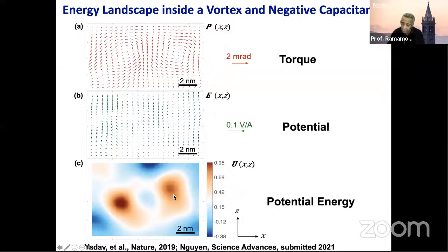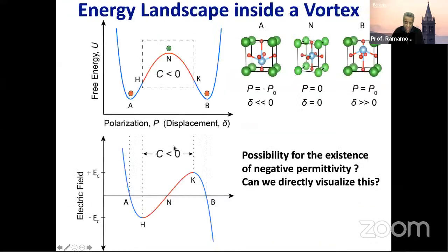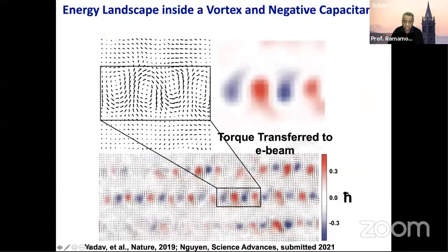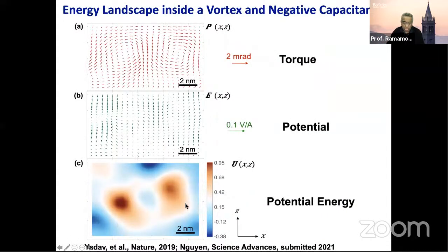And therefore, you could see that somewhere between these two, there is a maximum here in potential energy, another maximum here, and the minimum is here. Okay, and so you could envision that you have created a structure that looks exactly like this, but at the scale of one of these vortices, at the scale of a few nanometers. This length scale is of the order of 5 nanometers.